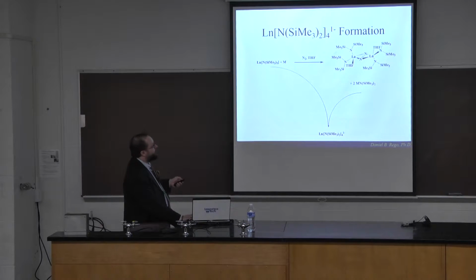We are actually able to form this. We can see the proton signal in the NMR, but we just have not been able to crystallize it with this ligand because this is just so large that it allows another amide in. The smaller lanthanides don't, which is why you don't form this and you end up getting a lot of this compound.